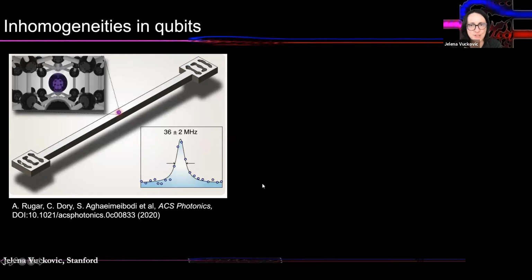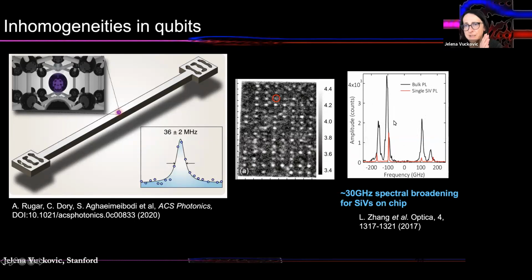I mean, nothing is perfect. You always end up with some inhomogeneities. Even if you have the best process, you always have some spatial inhomogeneities, right? You can't always with 100% yield incorporate these impurities at desired spots. Or you have some spectral inhomogeneities, which would come from imperfections in the surrounding environment, because this is not anymore an atom or ion in vacuum, right? It's beautiful that you don't need to trap it, but there are phonons, there are other atoms, so any damage, any strain, any imperfections would lead to a change in the transition of that atom and inhomogeneous broadening. But at best, we can actually reduce this inhomogeneous broadening of the transitions to about 30 gigahertz, which is still something that, as you'll see in a moment, we can control with a variety of tuning methods.